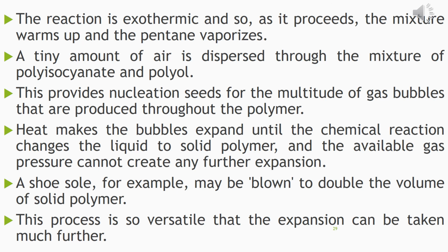Meanwhile the chemical reaction changes the liquid to solid polymer, and the gas pressure cannot create any further expansion. It is expanded only up to that extent. A shoe sole, for example, may be blown to double the volume of the solid polymer.